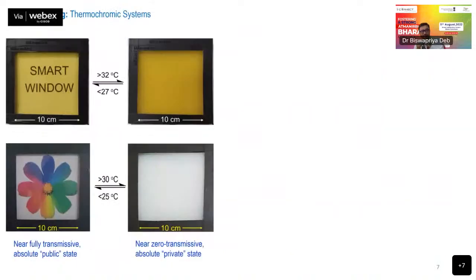This is a passive glazing technology, a thermochromic technology. These devices are fabricated by filling a special liquid formulation between two normal silicate glass panels, and they operate on the basis of lower critical solution temperature. So you have a target critical temperature, let's say 30 degrees. Below that temperature you have a fully transmissive public state, and above that temperature you get a completely private state.